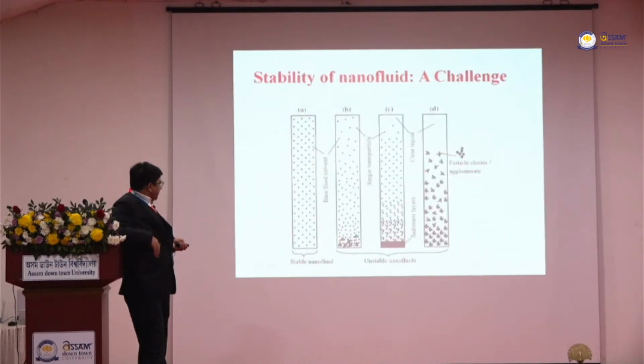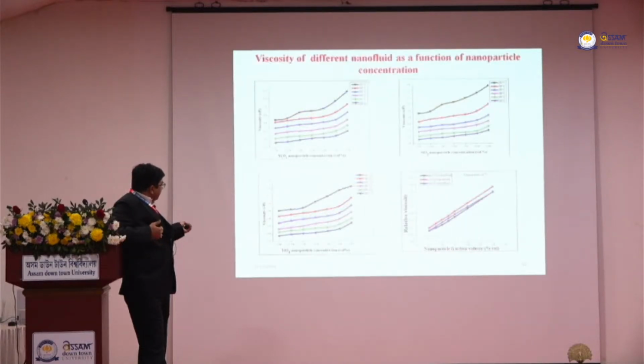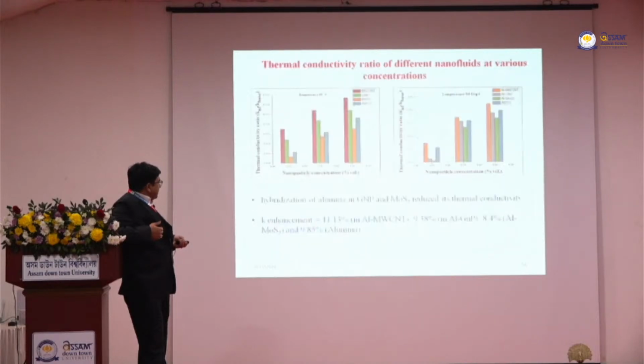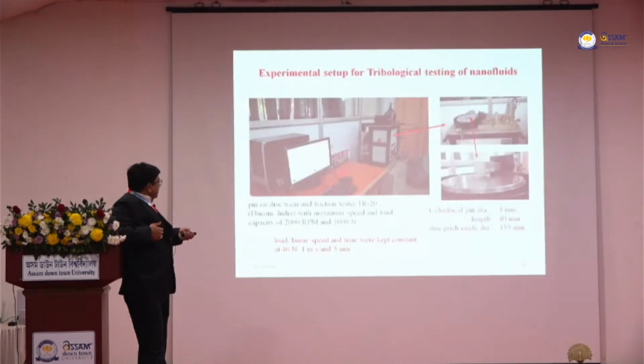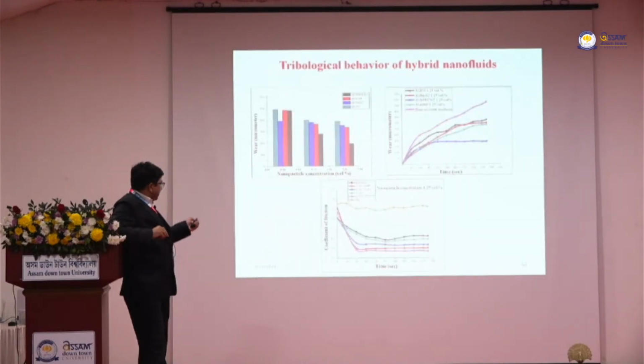We did characterization of cutting fluids. Then we got some curves, how they are behaving with the increase of percentage and increase of temperature. So I'm not going into detail. This is the tribological setup where we investigated the impact of adding nanoparticles into the cutting fluid. So we got encouraging results. You can see this is the dry condition where the coefficient of friction was more than 0.5, and while using MWCNT hybrid nanofluid, you can see it is less than 0.1. So it means tribologically it is better.